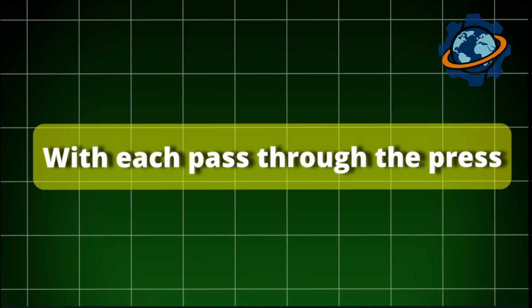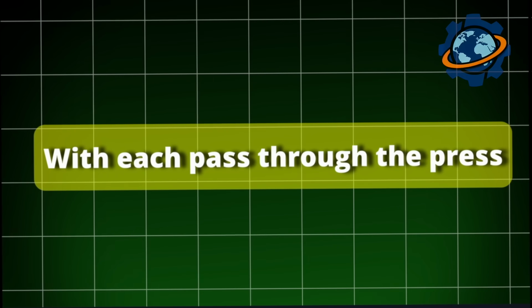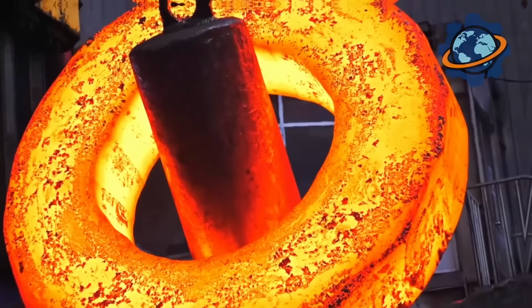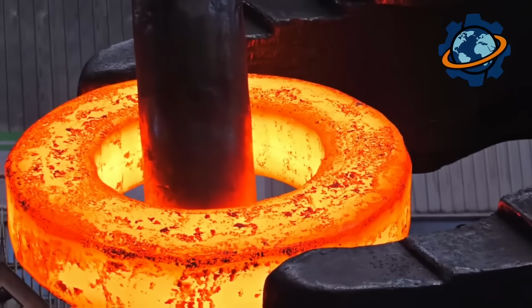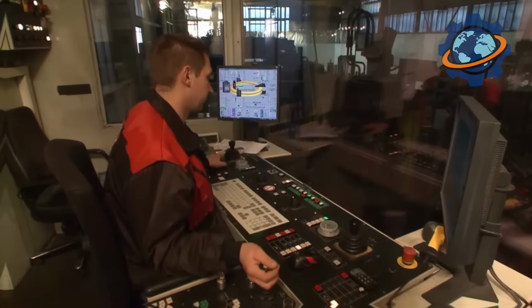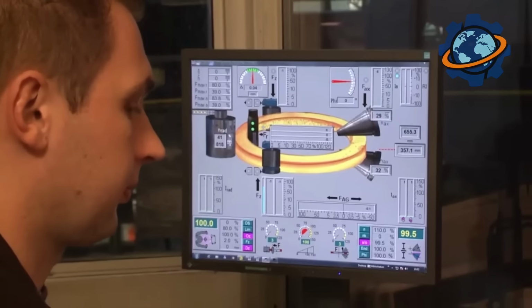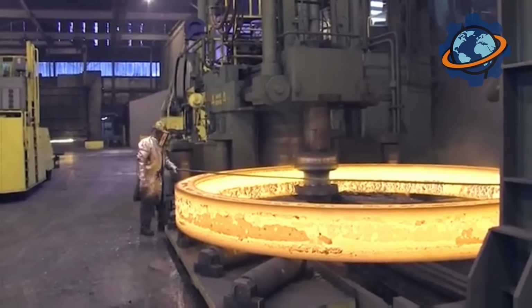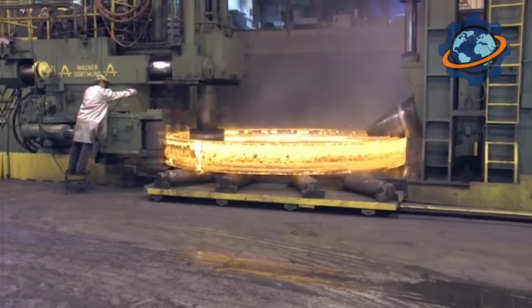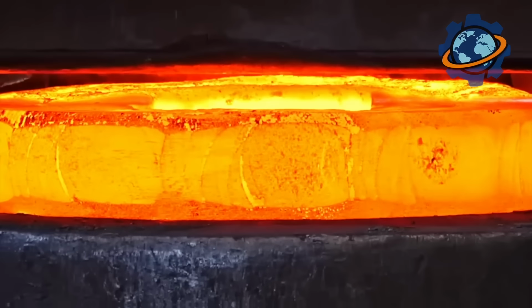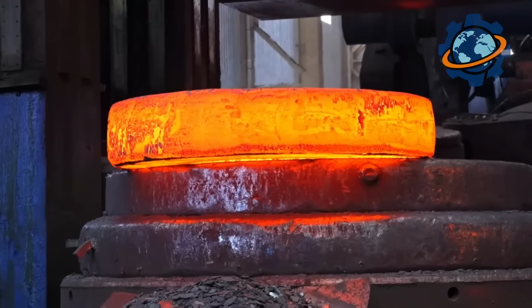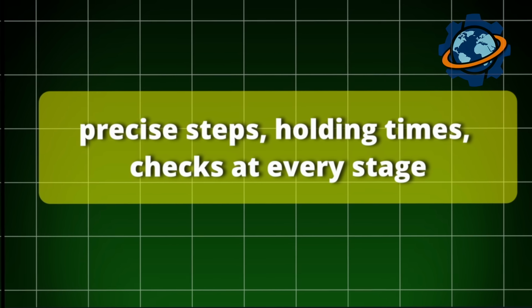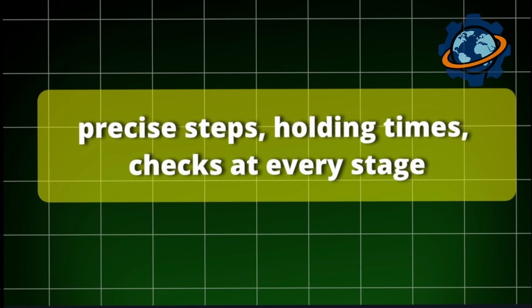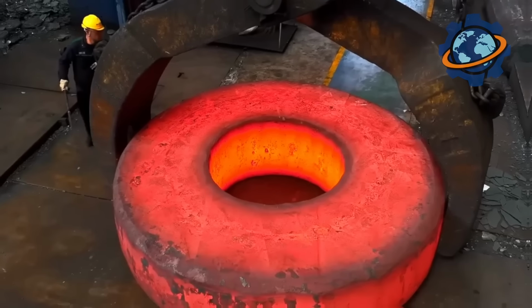With each pass through the press, the ring grows in diameter, but its walls maintain the required thickness, and the steel's grain structure aligns. Engineers constantly monitor temperature, compression force, and deformation rate. If the metal cools too much, it becomes brittle and can crack. If it overheats, the structure flows and the steel loses strength. So the entire operation is run like a complex recipe. Precise steps, holding times, checks at every stage. In the end, you have a solid ring without a single seam.